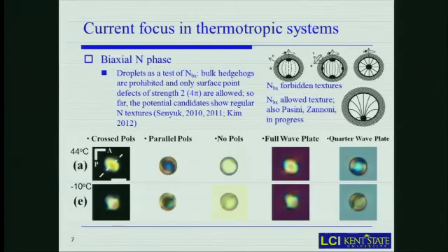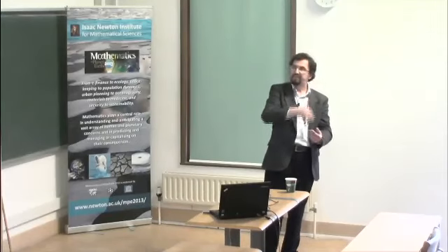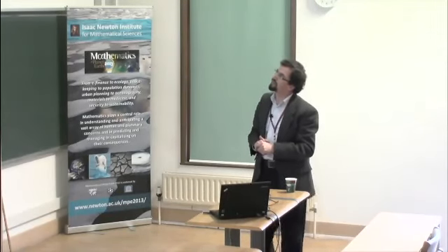And you know that if you have a sphere and the vector field is defined on this sphere, by the Poincaré theorem, you cannot have a smooth vector field. You must have 2 poles or one defect that represents a junction of these 2 poles. So this particular texture would be impossible, and bipolar texture would also be impossible, because if you have the director that is tangential to the interface, then the secondary director would form a disclination, that line defect that connects the 2 point defects along the axis.